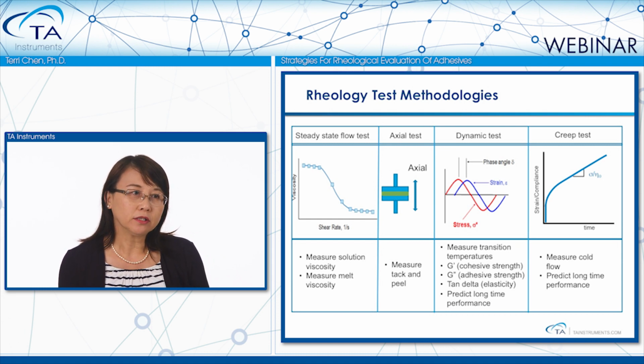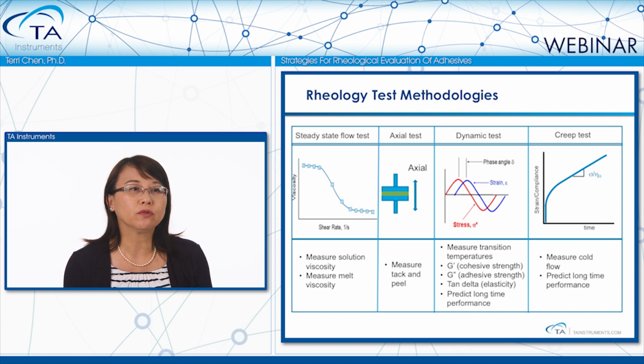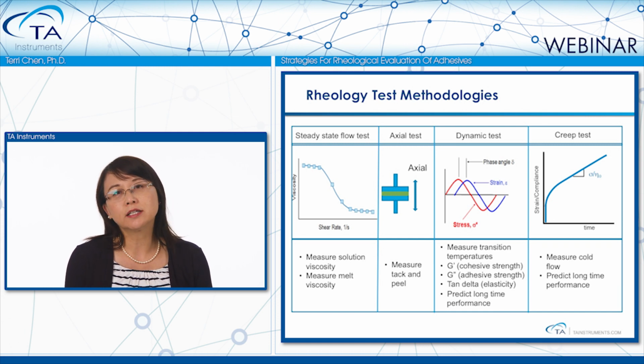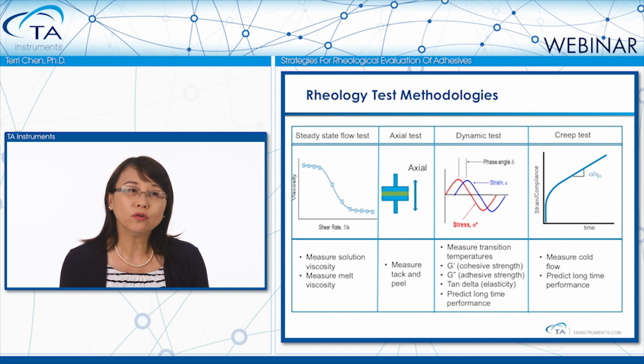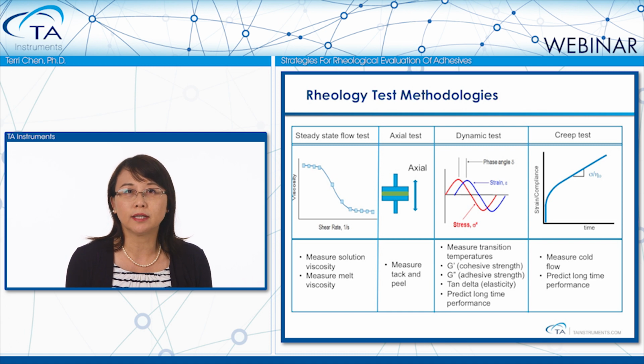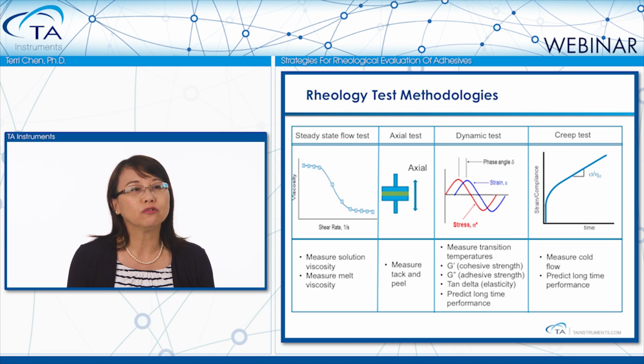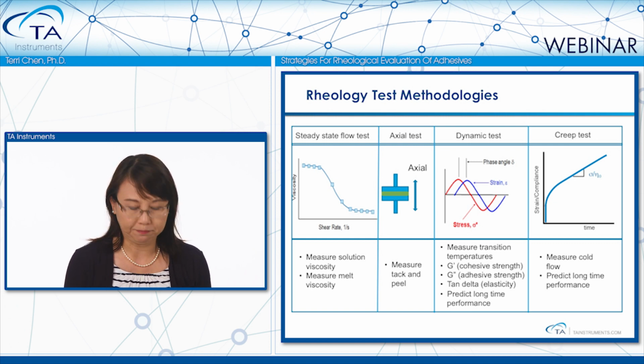The dynamic oscillatory tests are the most popularly used tests in adhesive analysis. First, this measurement measures the transition temperatures, such as glass transition. Also, the measured parameters, such as G', G double prime, or tangent delta, are directly used to correlate with the adhesive performance. A creep experiment can also be applied to directly measure the shear resistance, how good of an adhesive to resist to a cold flow over time.